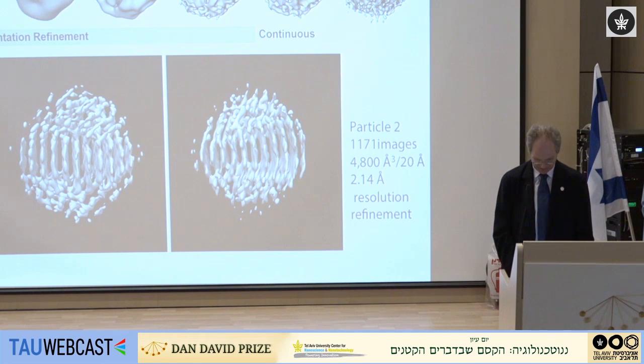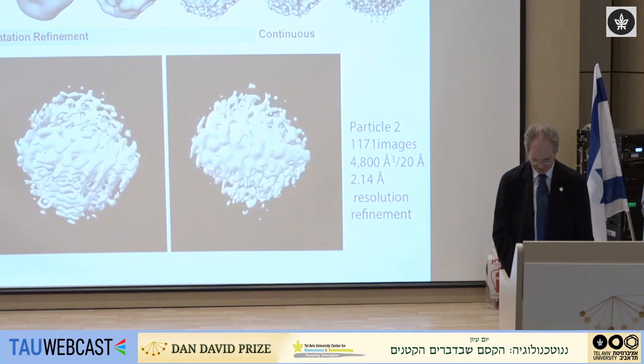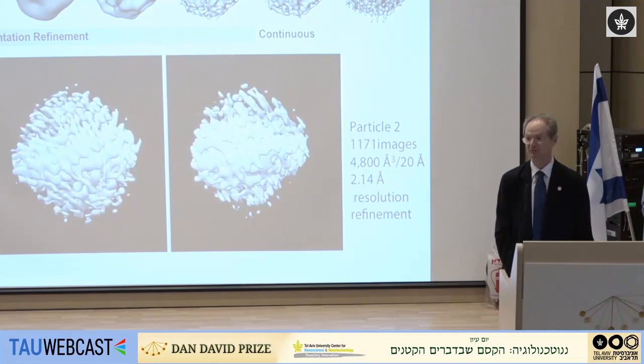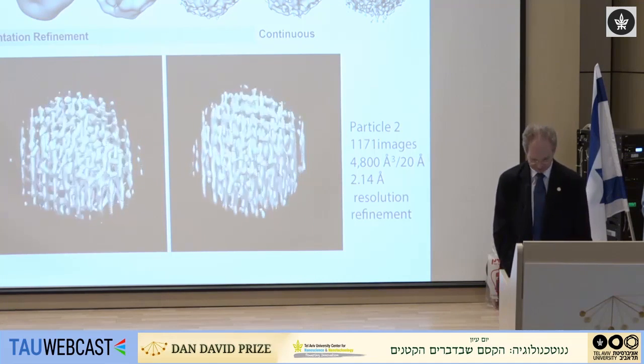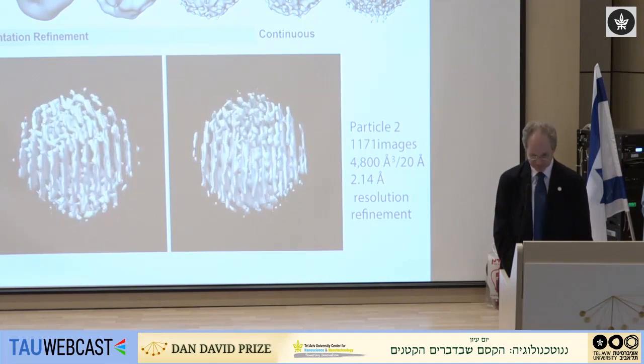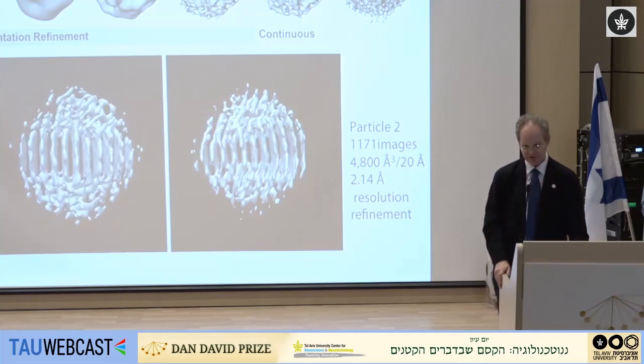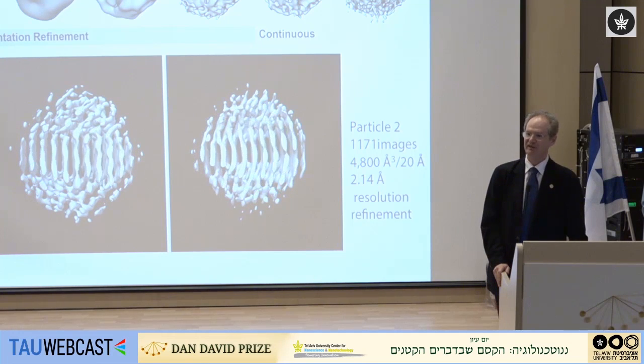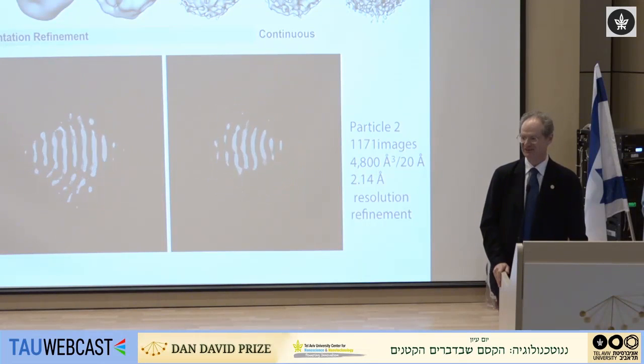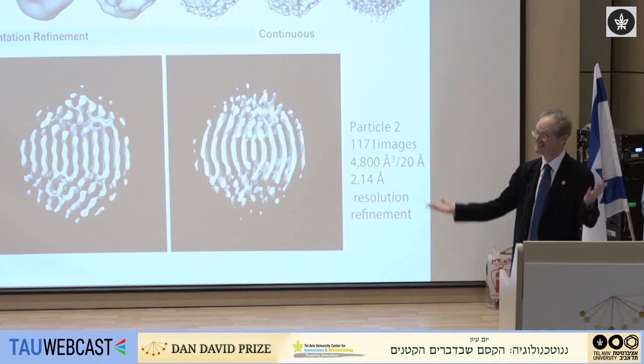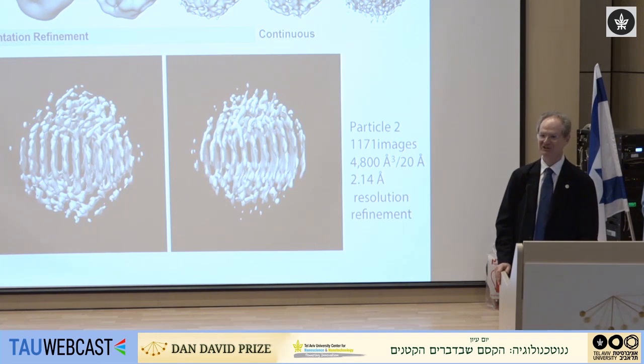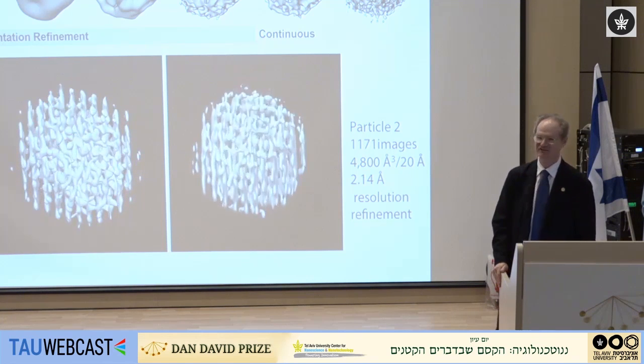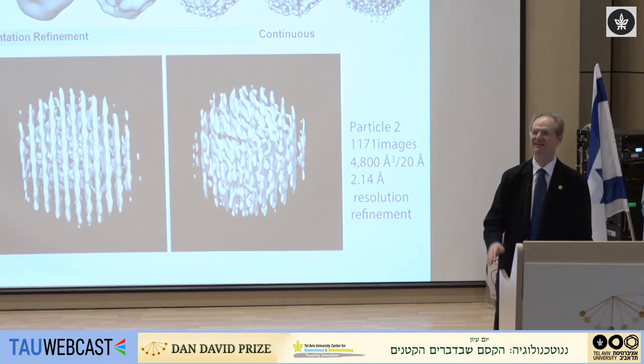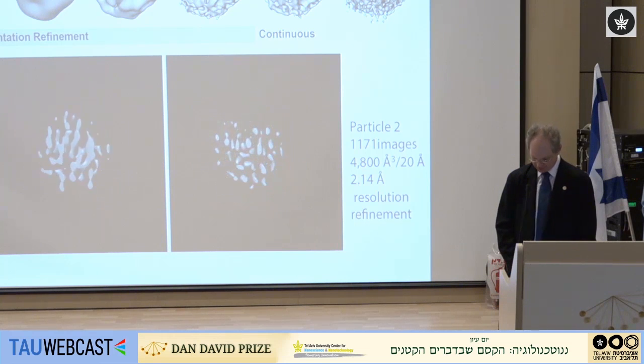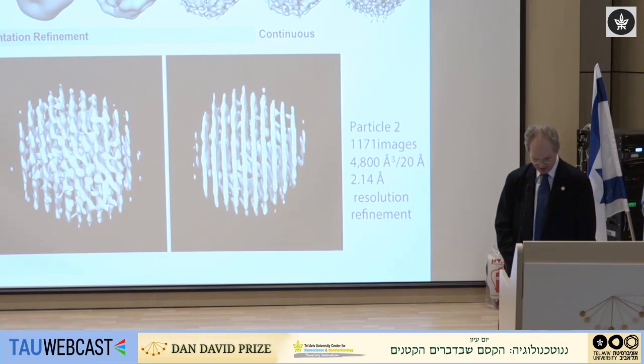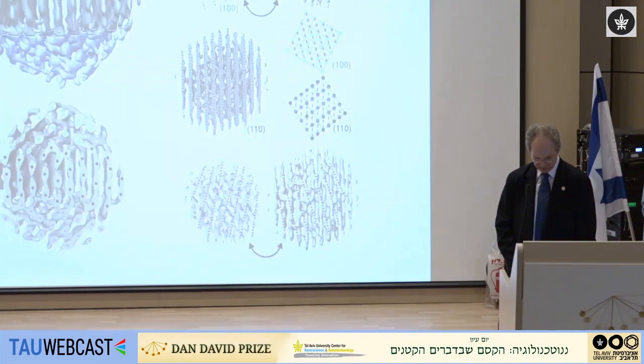And what we can get is the position of every atom in the crystal to a resolution of just a little bit worse than 2 angstroms, 2.14 angstroms. Now, the reason this is important is because the nanocrystals that we know how to make, no two of them are absolutely identical the way proteins are. They just are not, because we're not as good as nature is at making stuff with 1,000 atoms yet. But we are going to learn, and we'll get better at it as time goes on. And the way to get better at it is to observe single particles.